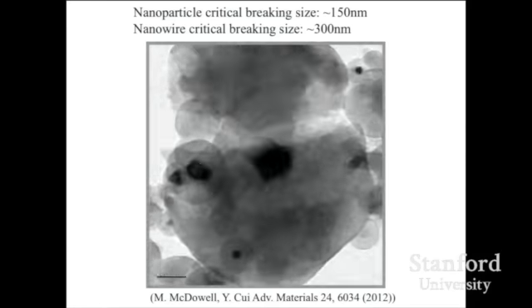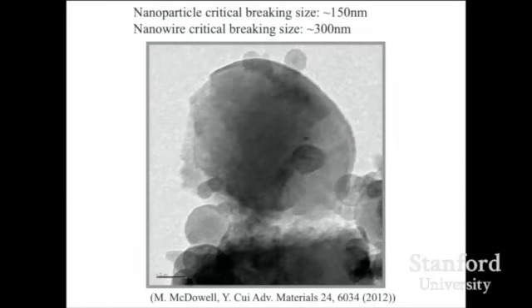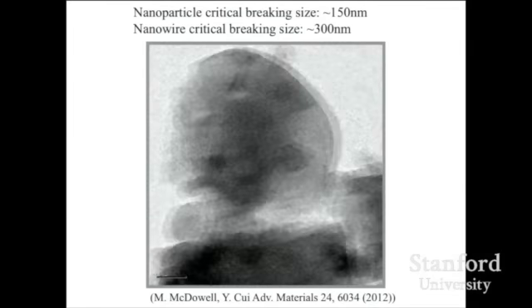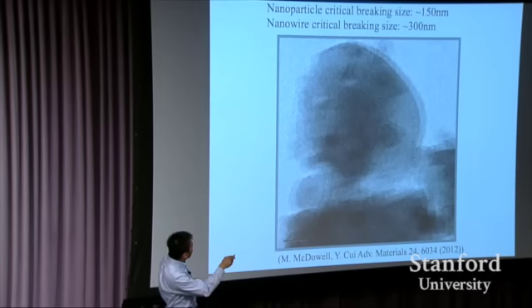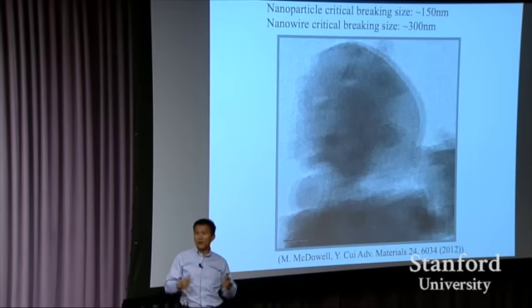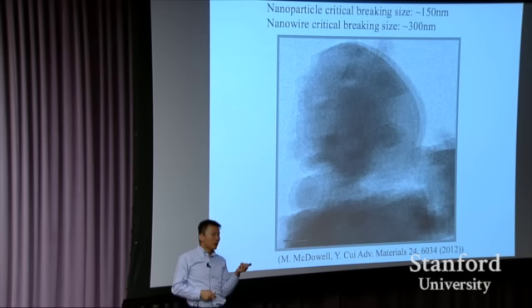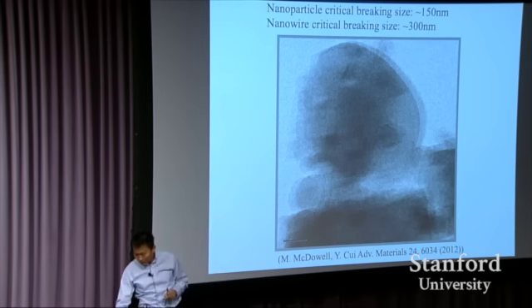Once this pops open, game over, the batteries die. So now we also found out the critical breaking size for nanoparticles is 150 nanometers, and for nanowires 300 nanometers. We know what size we are targeting in order not to have the breaking phenomenon.